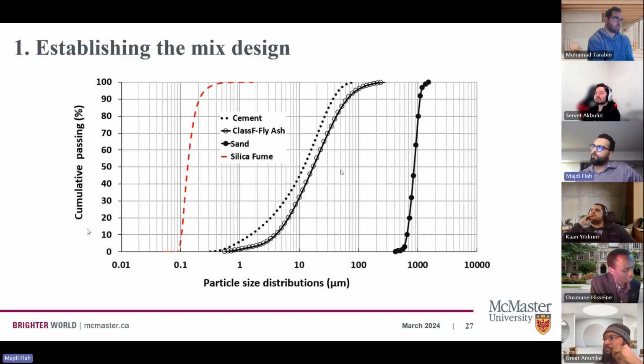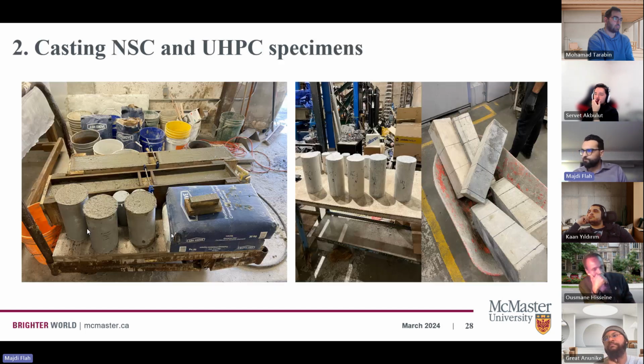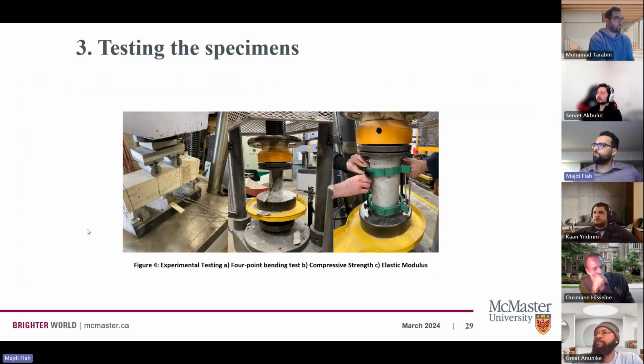So now we'll move to our experimental study. We started first by establishing the mix design. We did the particle size distribution. We tried to have a wider distribution for our particles. The particle size distribution was optimized using the EMMA software and using the modified Andreasen model, and the factor Q was equal to 0.21 for this study. So we went to the lab. We cast all the different specimens we have for the modulus of elasticity, for the compressive strength, and for the flexural strength. So these are some pictures from our studies.